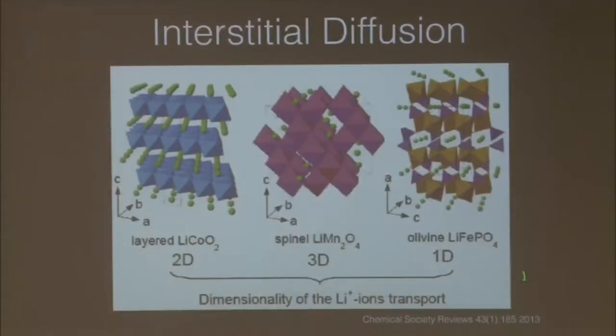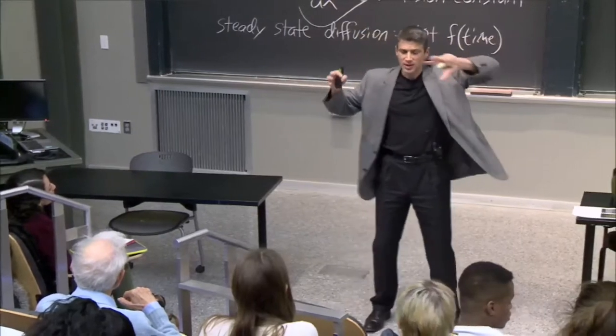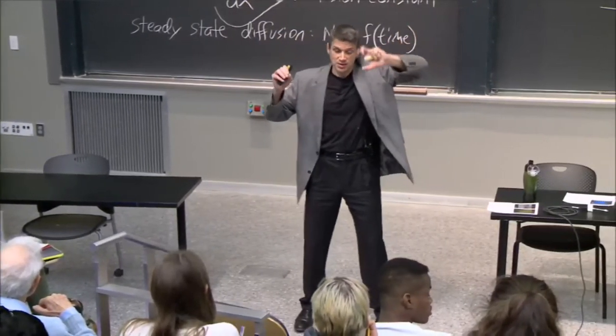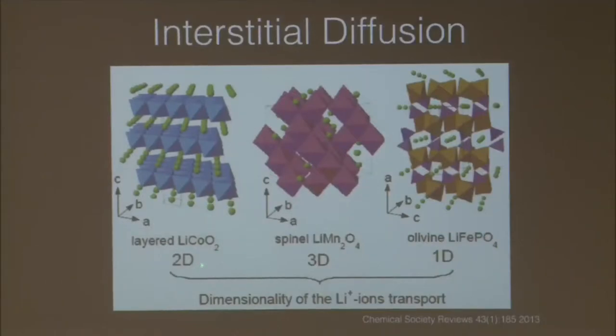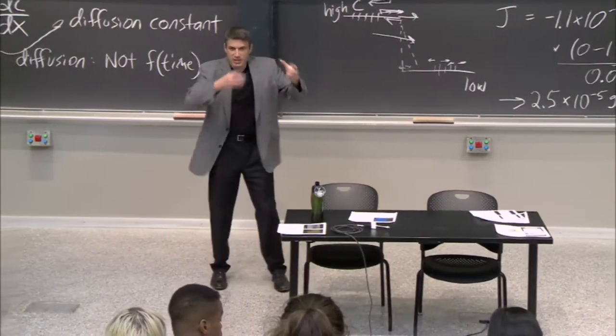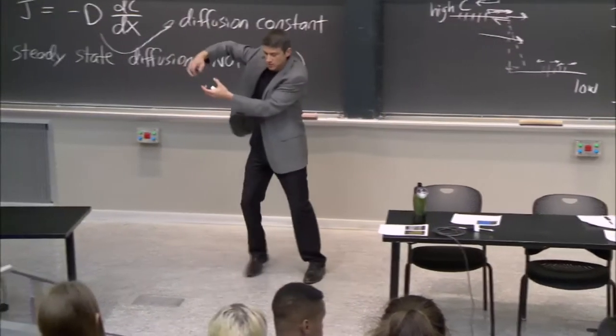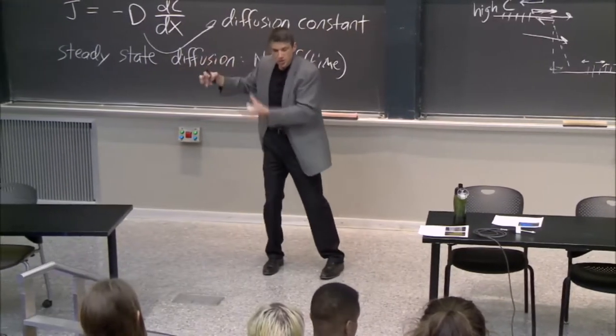You've got lithium iron phosphate, manganates, cobalts, cobalt oxide materials — there are so many battery materials. They all work the same way: in a lithium battery, lithium is going to leave some crystal that has lithium in it, but the crystal has to stay. So it's like a sponge that loses something from it but stays intact, and that something goes over to the anode, where it gets soaked up.